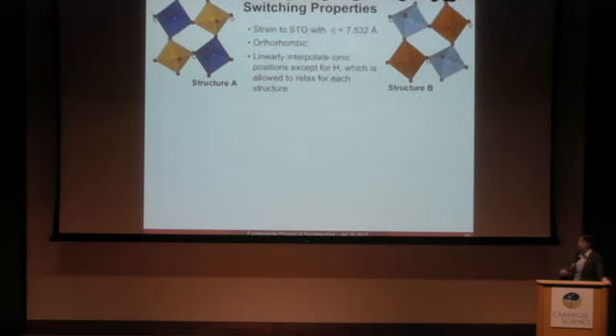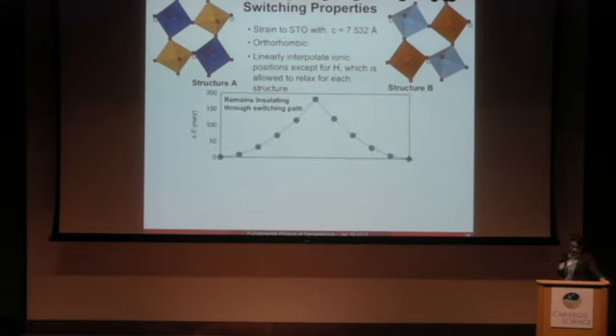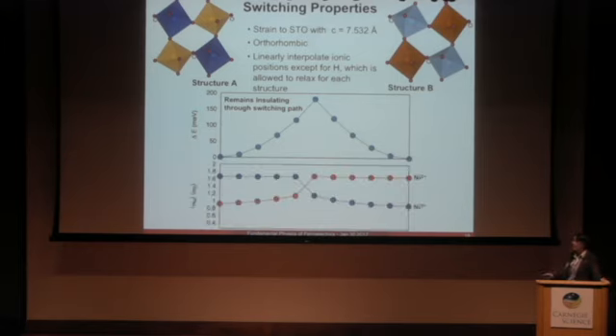So if we have this orthorhombic structure, we can switch from one to the other by linearly interpolating the structures. It remains insulating throughout. We have an energy barrier that's a little high, about 200 meV, and we can see clearly that the magnetic moment switches between the single electron and the double electron.